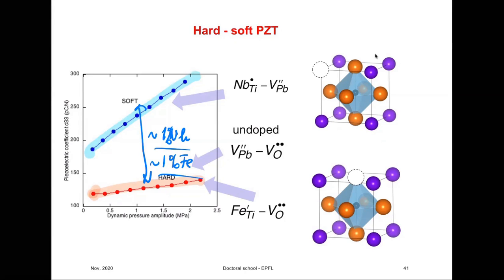And it is also possible to have other dopants. You can produce soft materials by doping hard materials on an A site, and it doesn't have to be a B site dopant, but for simplicity, I'm discussing these cases. So a dopant can go on the A site, both to make the material soft, for example, lanthanum in a PZT will make the material softer, and for example, potassium on the lead site would make the material harder.